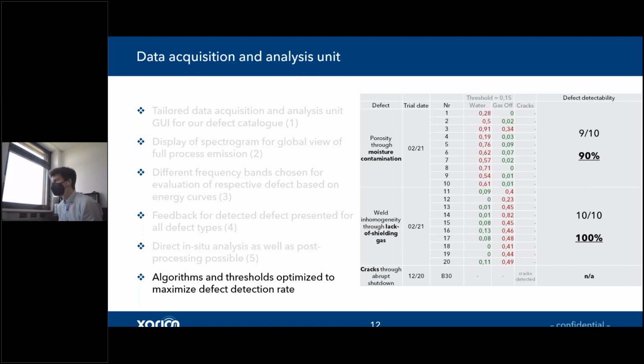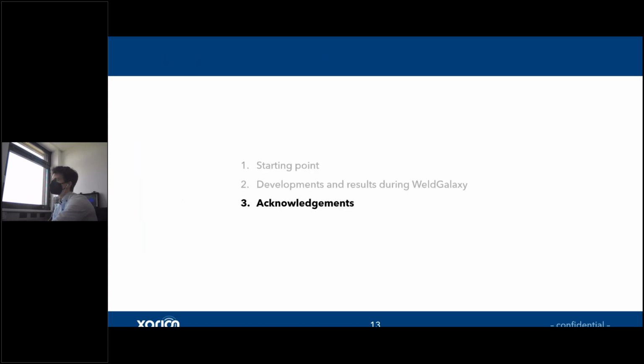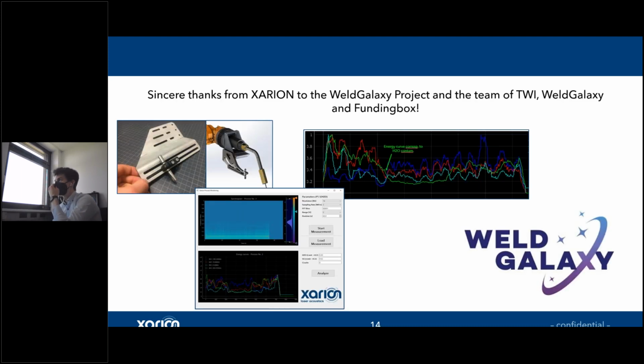So with the moisture and the lack of shielding gas, it was quite easy to determine a direct defect detectability rate, because we know exactly when the defect was present, and we could then correlate it with our acoustic signal. With the cracks, it's actually not so easy to see them on the visual and the X-ray. We did, however, confirm on an audible basis that cracks occurred, and we also detected cracks. So that's already the sum up of the project.